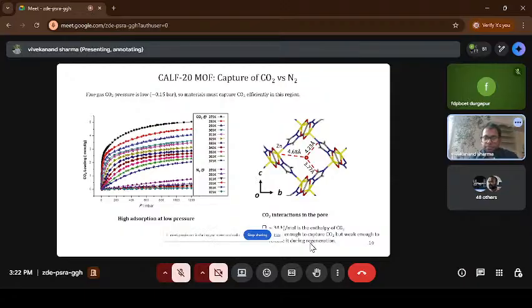Also, the enthalpy of CO2 adsorption comes around 34 kilojoule per mole. So this energy was in the moderate range, not too high, not too low. The moderate range indicates a favorable interaction of the carbon dioxide gas with the material, and it also indicates a lower regeneration cost. It is not very difficult to take the CO2 gas out of the material once the material is fully saturated with carbon dioxide gas.